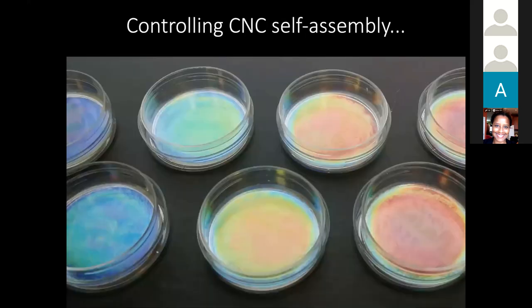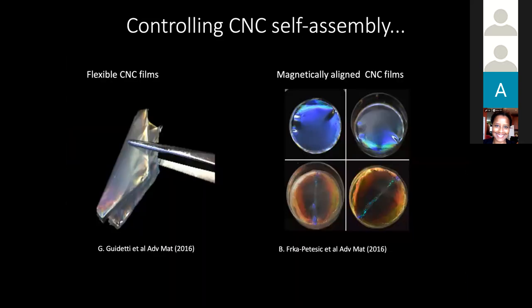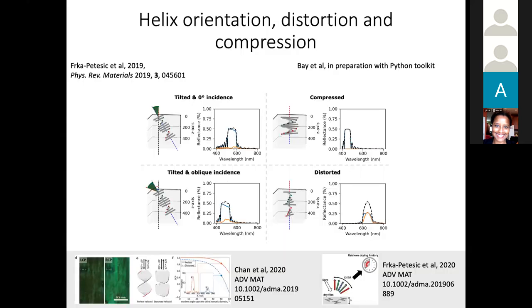So now we have worked quite a while with the system. By changing the condition of the assembly, by adding surfactant or salt inside, you can really change and screen this interaction because they are a colloidal system. And as a result, you can also change the color. So you can make color from blue to cyan to more green, yellow, orange, and red. And in principle, you can even do ultraviolet and infrared. By playing a bit with the self-assembly, you can improve the alignment. You can also improve the mechanical property, make them a little bit bendable. We can change the response.